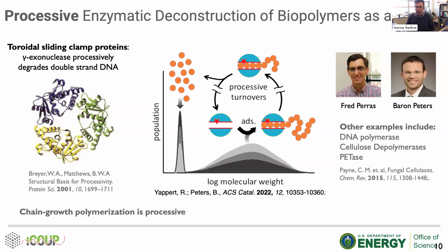So we were thinking, and I should say here I would give heavy credit to Baron Peters at UIUC now, who said, well, how does nature do depolymerization reactions? And he and Fred Perras in the Ames lab pointed out that there are lots of enzymes that depolymerize biopolymers, and they do it through what's known as a processive mechanism, where the enzyme catalyst will adsorb a polymer chain and start eating it up, and the substrate polymer or biopolymer isn't released until all the monomers or whatever the units are that the enzyme cleaves have been cleaved off.